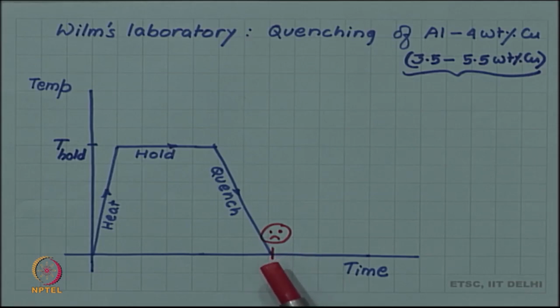And when he resumes, when he repeats his experiment, when he measures the hardness of the specimens which were quenched on Saturday but whose hardness was not measured, and he is measuring the hardness on Monday, he finds an increase in hardness. Hardness has actually increased.